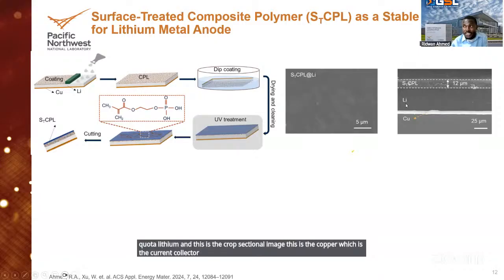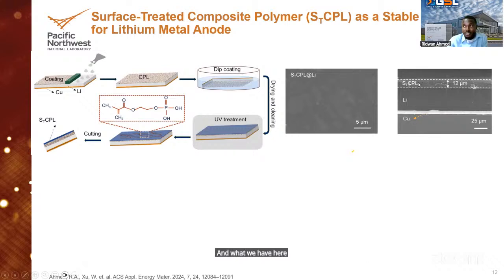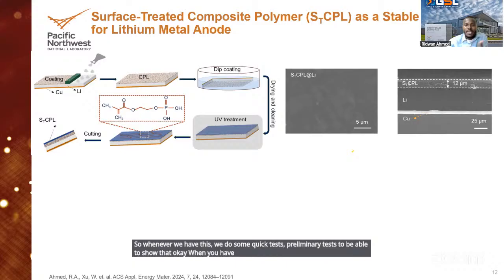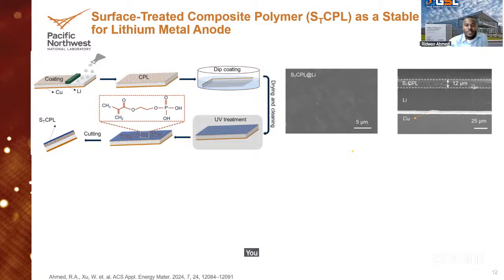The dark region here is the lithium. And what we have here, STCPL, is the coating. So whenever we have this, we do some quick preliminary tests to show that when you have this in your batteries, you can achieve better stability or improved performance.